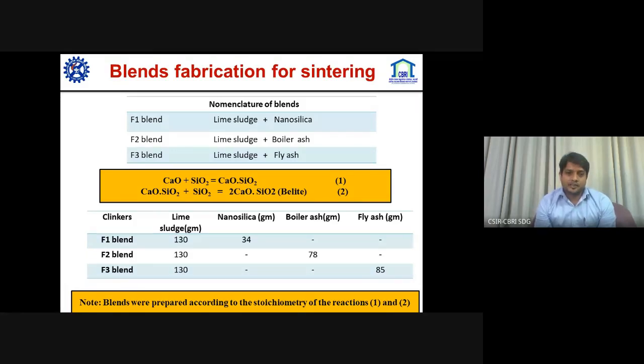So on the basis of this, keeping the molar ratio of calcium and silica up to 2, on the basis of stoichiometry, these blends were formed, in which nanosilica was 34 grams, boiler ash was taken up to as 78 grams, and fly ash 85 grams.